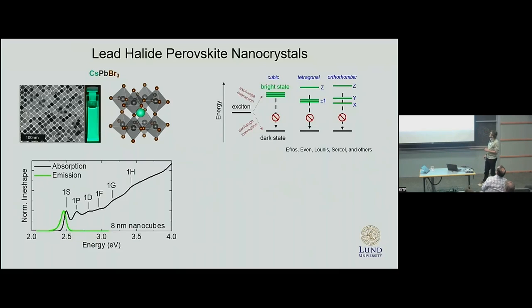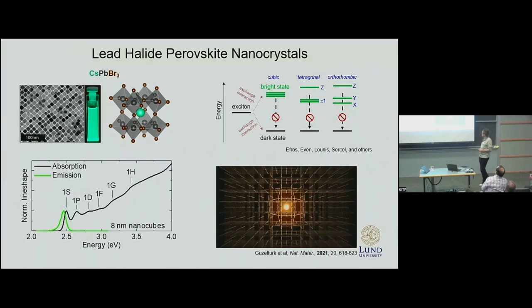There are a couple of things which are unique to them. First is their electronic structure, such that, for example, they have a bright state at low temperature with a transition to the lower energy dark state inhibited, in contrast with II-VI nanoparticles. Another interesting property is that they form polarons after photoexcitation, meaning electron-hole pairs polarize their immediate environment and in that way are stabilized. That's what underlies, for example, the remarkable efficiency of perovskite solar cells, since these are ionic semiconductors and not covalent.